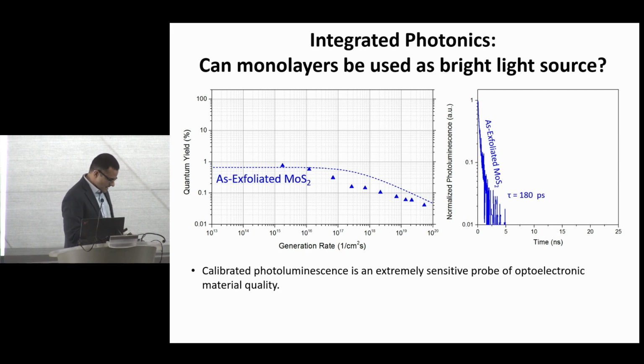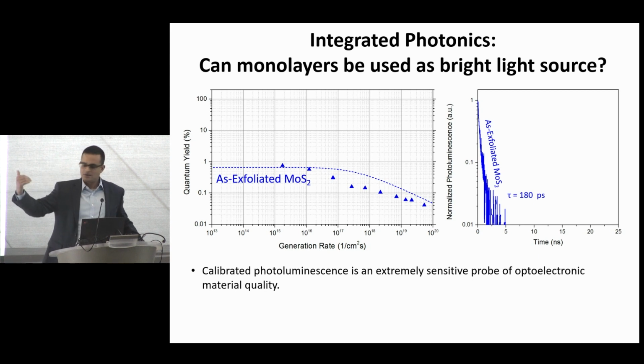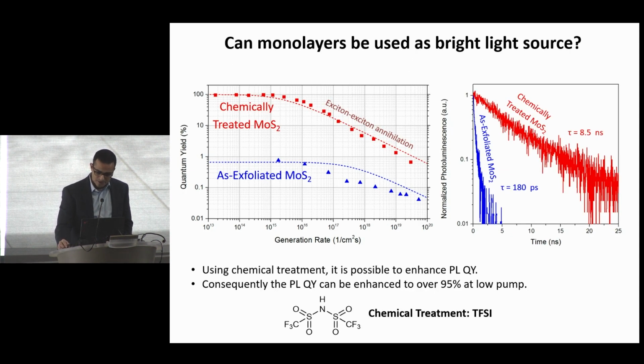So the starting measurement that you always do when you're trying to build light-emitting devices is photoluminescence quantum yield measurements. And the maximum device efficiency, if you build the LED, will be your quantum yield minus all the other non-idealities that come about when you build a device. So when we looked at moly sulfide as processed, the quantum yield we saw was extremely poor, less than 1%. So if you build the LED, it will be less than 1%.